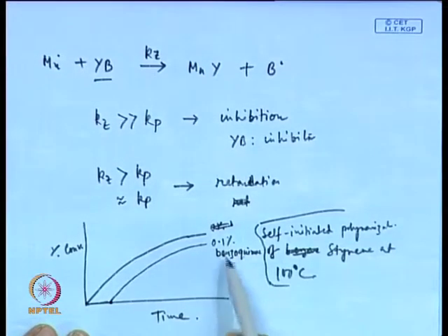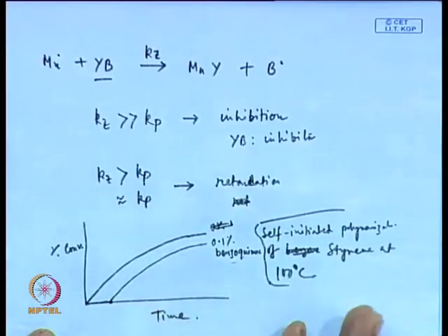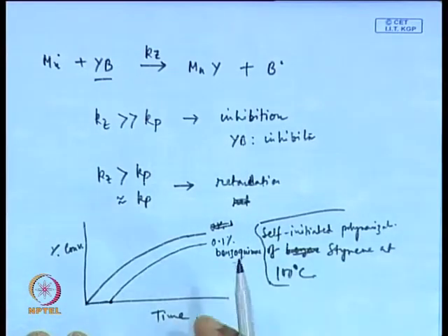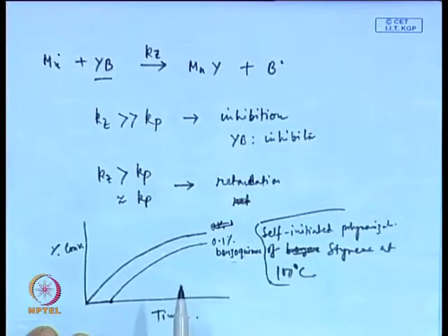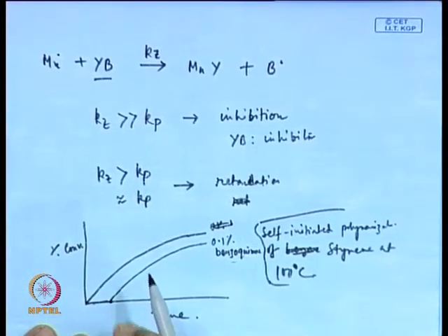Now, this is a typical example of how common monomers are shipped or stored, because most monomers, when they are shipped between different countries or locally, are stabilized with a small amount of these inhibitors, for example hydroquinone or benzoquinone, because they should not self-polymerize either by a little bit of heat from the ambient or by self-initiation reaction. So, when you do a reaction, the best way is to distill out that benzoquinone or hydroquinone stabilizer or inhibitor, or you can add a little excess initiator compensating for the inhibitor molecule, so that the reaction doesn't proceed till all the benzoquinone or hydroquinone gets consumed, after that normal reaction happens.